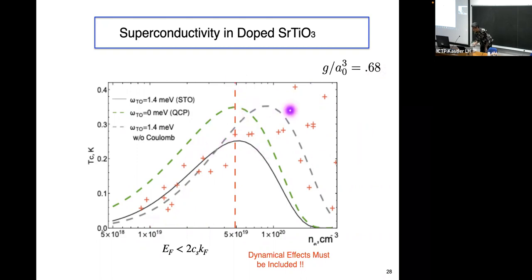We can push this. I'm running out of time, so I'm just going to say our calculations are only good until here. This is where the dynamical effects that Andre was talking about at the end of his talk on Monday have to be included. So EF is less than CS KF below that line. Above, we have to include the electronic contributions to the dielectric constant and look at the frequency dependence. As we learned from Andre, the Coulomb repulsion will get stronger as we increase the frequency dependence. The attraction will go down. And so you're going to have the interaction change as a function of frequency. And so you can play some games with retardation. Okay, we haven't done that yet. Okay, did I get that right, Andre? Good. See, I listened to you too.